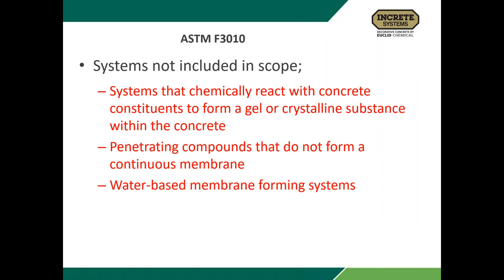The systems not included in this ASTM designation are chemically reactive constituents that form a gel or crystalline substance within the concrete. So any of your silicates or things like that that want to penetrate in and supposedly react and form something in the pores of the concrete do not constitute a vapor mitigation coating. Also excluded are penetrating compounds that do not form a continuous membrane. They say this over and over again.